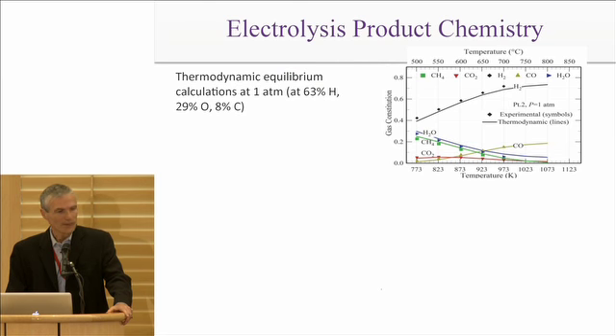Okay? And the key thing is, though, what are the products of that reaction? And what the key is, actually, as it turns out, is the product of electrolysis. Okay? So if we do that with a mixture of steam and CO2, and we do it at a typical SOFC operating temperature, which is about 800 degrees centigrade, and we do just equilibrium thermodynamics, we see that the products are mainly hydrogen and carbon monoxide. So what we've done is just we've taken steam and CO2 and electrolyzed them to hydrogen and CO.